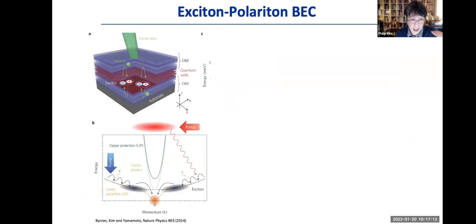For example, in semiconductor heterostructures, you create excitons in a quantum well, but you embed this exciton quantum well into an optical cavity, and the exciton can start to resonate with the cavity photon, and then you can create this combination of the excitonic state with the photonic state, often called the exciton polariton.